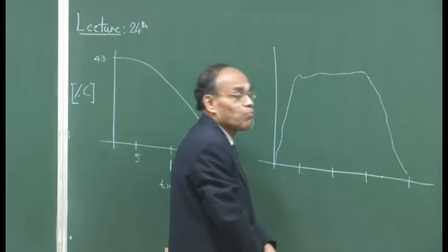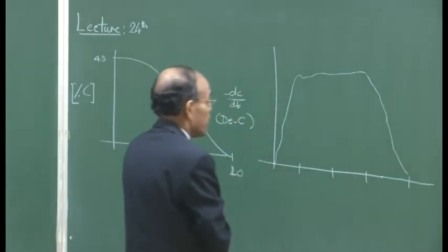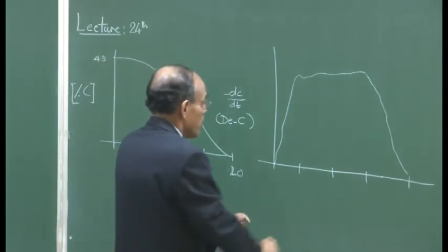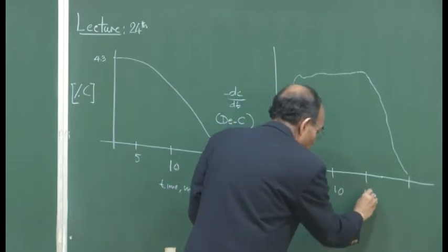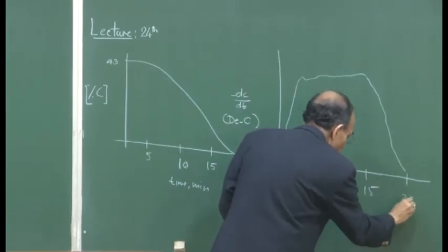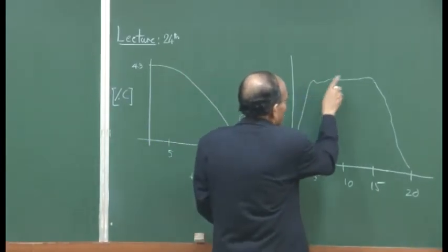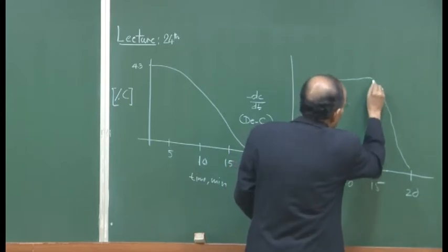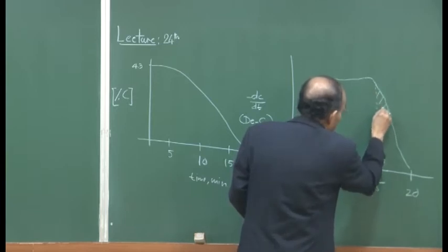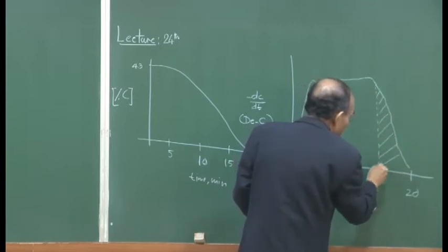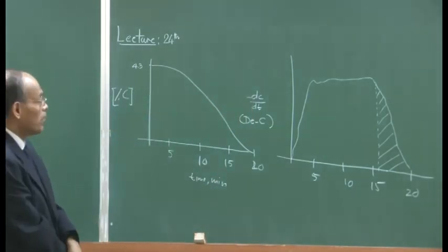And thereafter, you are supplying oxygen, but there is not much carbon. So, there is a mismatch, and the decarburization rate really falls as a function of time, and that is the same plot that we have. We are not interested in this part. In order to control, the most significant portion is this particular portion, how the decarburization curve tapers off, to be able to simulate this particular region very precisely.